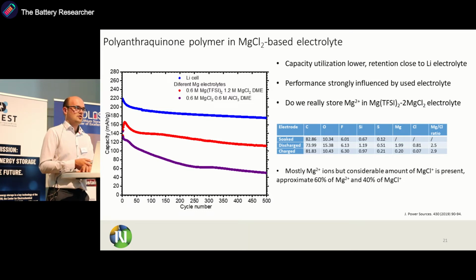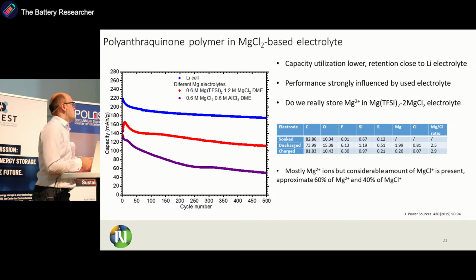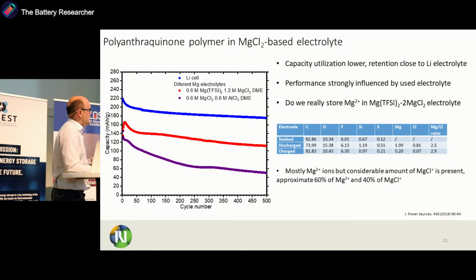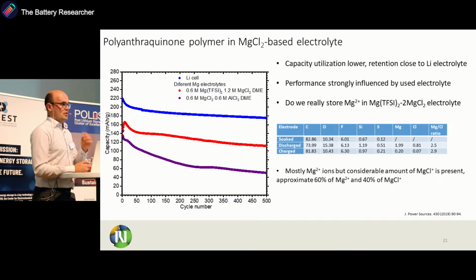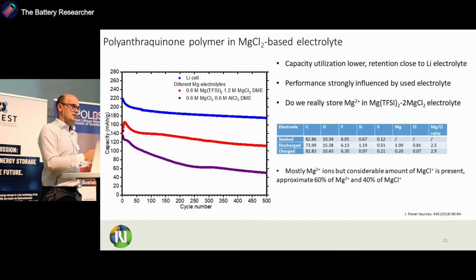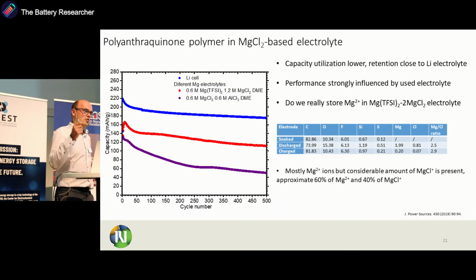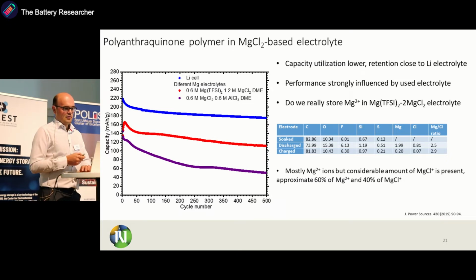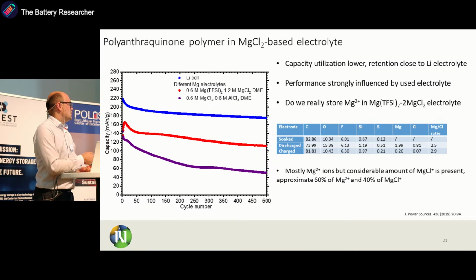So to investigate this, we used SEM-EDS ex situ, so basically to probe the elemental composition of the discharge electrode. And what is interesting here is that when we have the discharge electrode, we have both magnesium and chloride inside. And the ratio between them is around 2.5. So this means that we are storing both at the same time. We are storing magnesium 2+ and magnesium chloride plus. And the ratio between them is around 60% magnesium 2+ with 40% magnesium chloride plus.